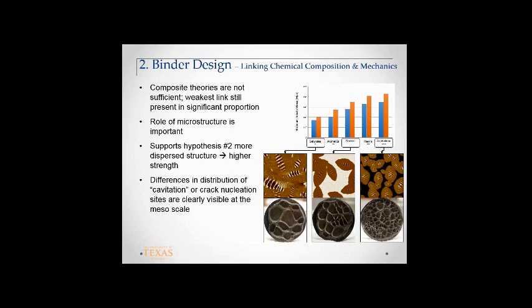This is an area of work we're still looking at, but what you see here, from that poker chip test, are failure planes. If you take the poker chip test and look at the asphalt, these are the failure planes you see. For the same set of conditions, you see how different this failure plane is compared to this one. Now, these little craters are referred to as cavitations or cavities. These are sites where cracks are born, and then they grow and coalesce with other cracks and form bigger cracks. If you compare these three systems, you'll see that there are many more sites here and very few sites here, and the only difference is composition.